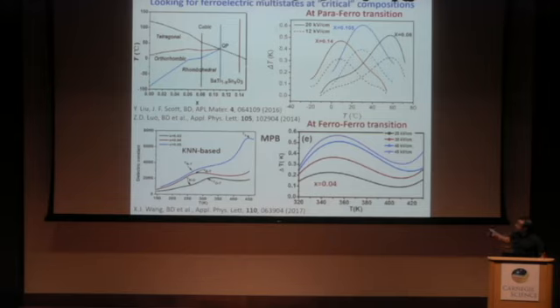It's not only related to paraelectric to ferroelectric phase transition. You can also have it in a ferroelectric to ferroelectric phase transition, it works also. So don't fix only on paraelectric to ferroelectric phase transition. You can find also, for instance, in this KNN-based system, close to the MPB, interesting change of the temperature.